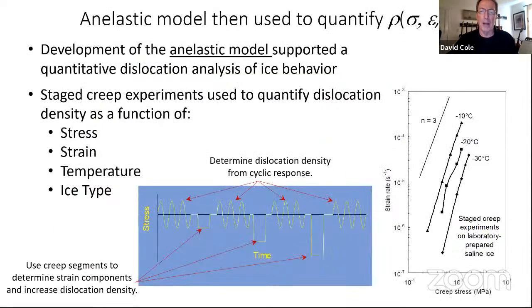Having that model allowed me to then use the anelastic model to track how the dislocation density increases, let's say, during a creep experiment. The basic test would be to apply some cycles, get a hysteresis loop area, calculate the initial dislocation density, and then run a creep experiment for a little bit.